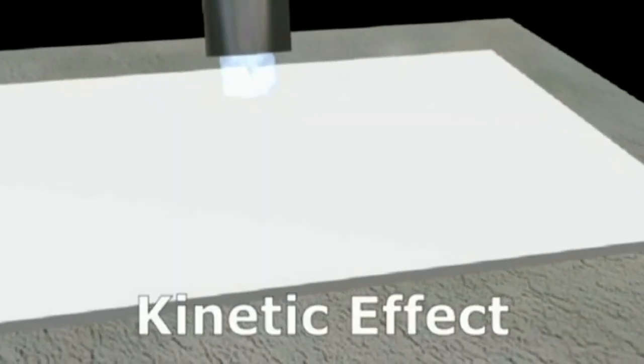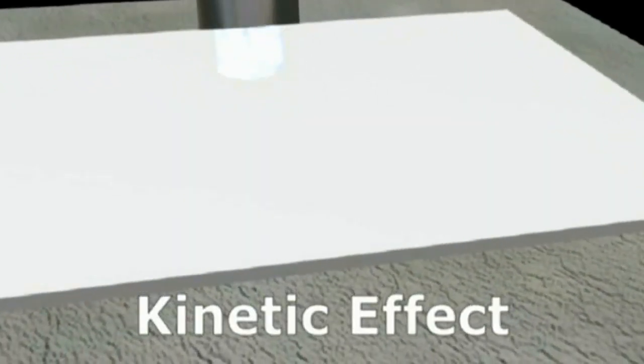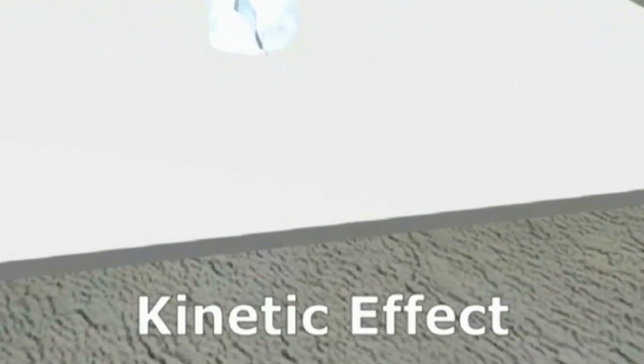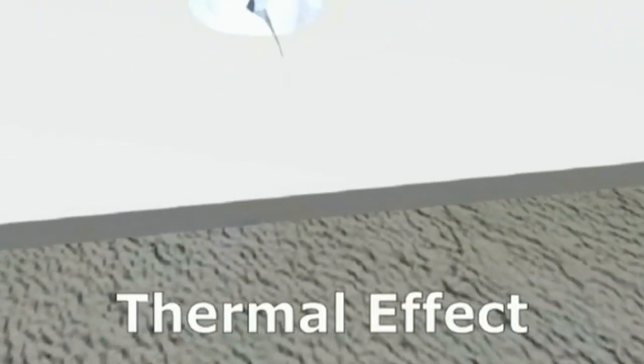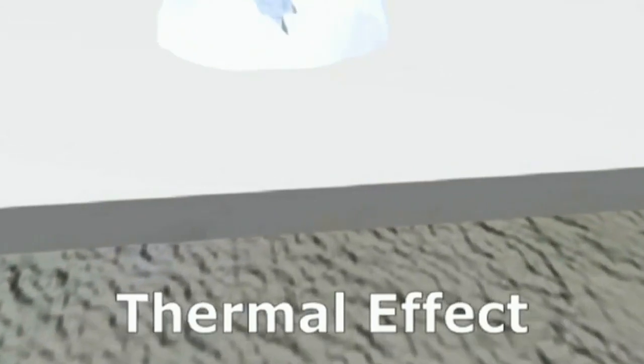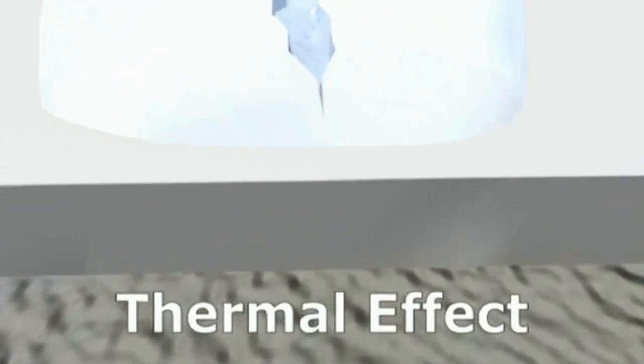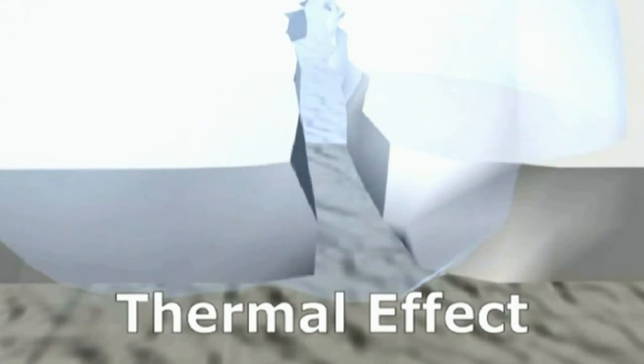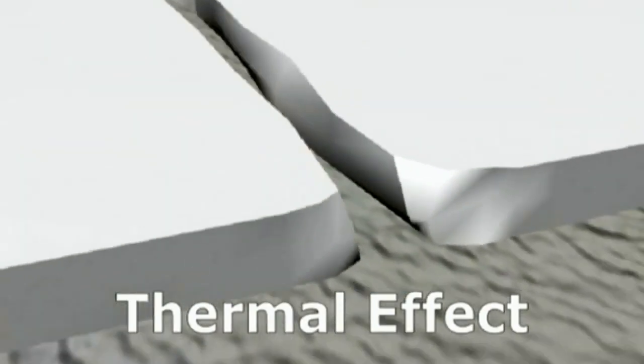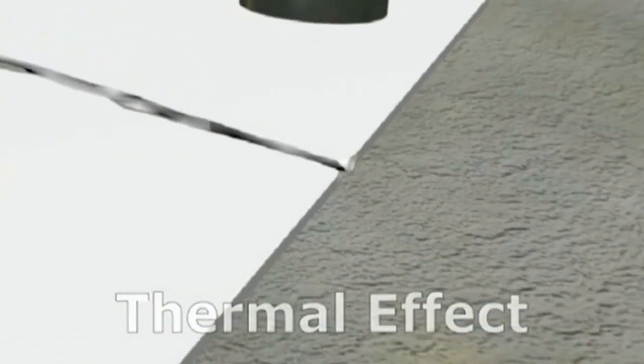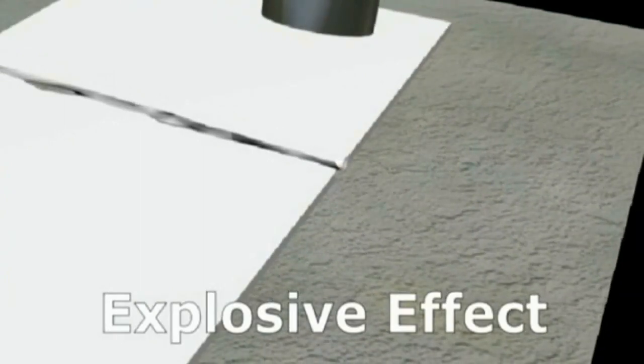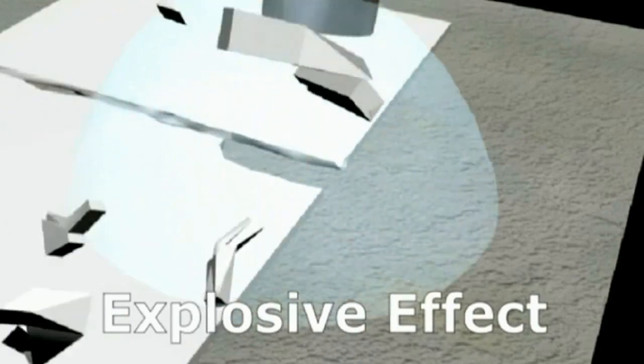When dry ice pellets strike a surface at the speed of sound, any coating on the surface is cracked and loosened. The low temperature of dry ice pellets makes the coating brittle, cracking and loosening it as a result of the reduced bonding between the coating and the underlying surface. This allows dry ice to permeate the coating. Dry ice penetrates the coating and immediately transforms directly from the solid to vapor state. This results in a 700-fold increase in volume, an explosive effect that lifts the coating off the surface.